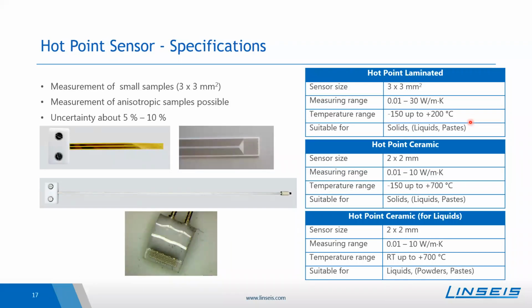Our third group, or our third sensor, is the hot point sensor. It is especially suited for the measurement of small samples, so samples of about 3 times 3 millimeters squared can be measured with it. Especially this is suited for anisotropic samples, where one can easily change the direction of measurement because only a small sensor area needs to be covered.